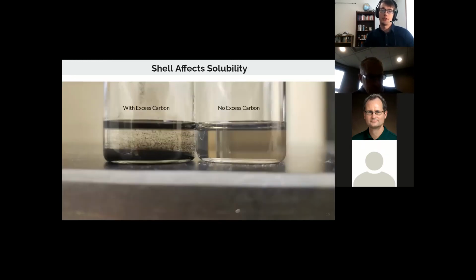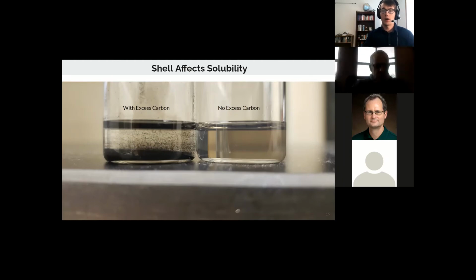To separate the particles from each other, the solutions were sonicated for 4 hours, and the particles that stayed in solution after being left overnight, or for about 8 hours, stayed in solution indefinitely afterwards. The nanoparticles generally went into solution in ethanol, which was described in other papers, as the silicon carbide nanoparticles have intrinsic solubility in ethanol due to their charge. The samples with large amounts of excess carbon would collect at the bottom of the vial if left to sit for adequate time. The particles did not dissolve in water without some processing, but they do in alcohols, indicating that the particles required a medium polarity solvent, or a relative polarity between 0.5 and 0.8. Indeed, they also dissolve in methanol and isopropanol.